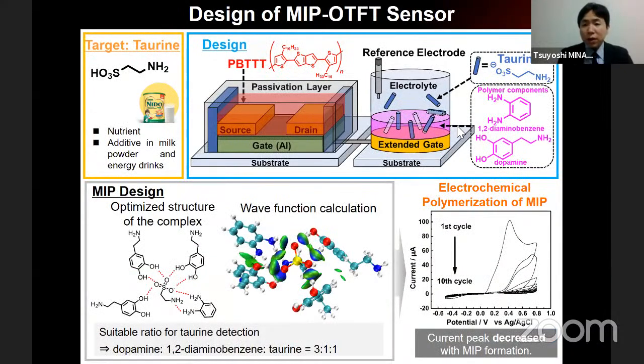So in this case, we use a diol compound and also an amino compound. They can be oxidized, and when they are oxidized, they can be polymerized. Make sense? For example, this is a cyclic voltammogram. When we apply the potential, first we can see the electroactive compound because the component exists. After we oxidize the components, they start to be reactive, and then we almost cannot see this cyclic voltammogram. These are the results.